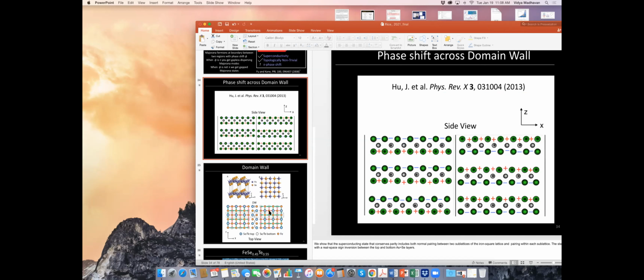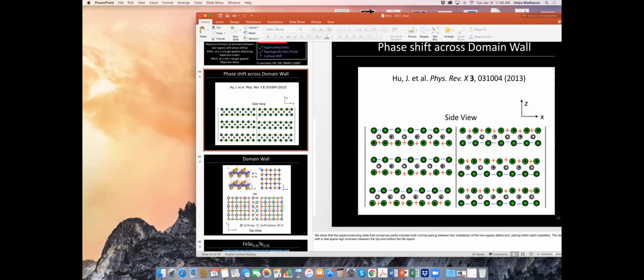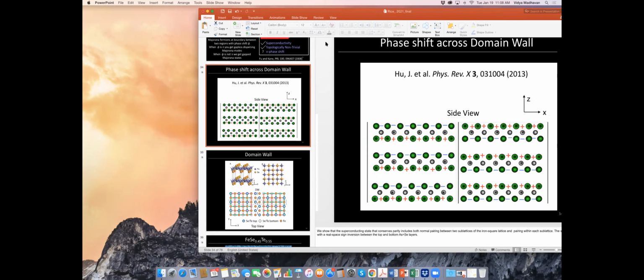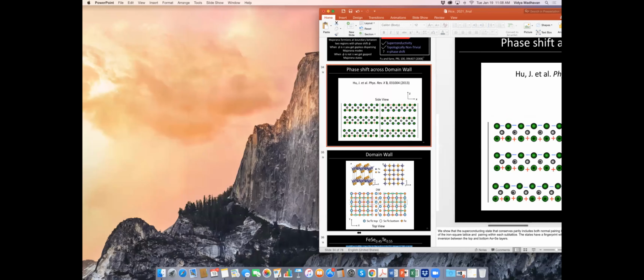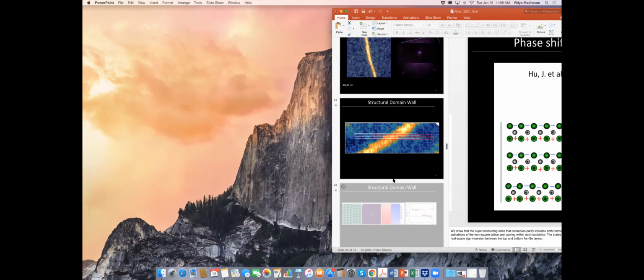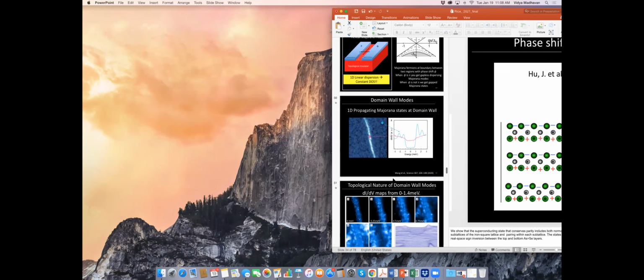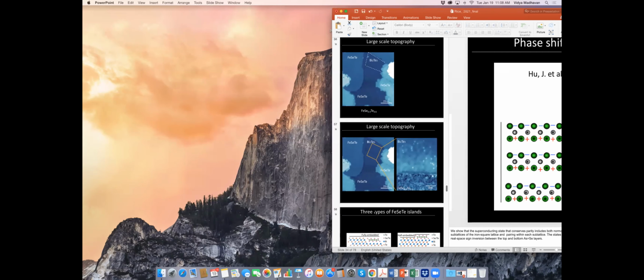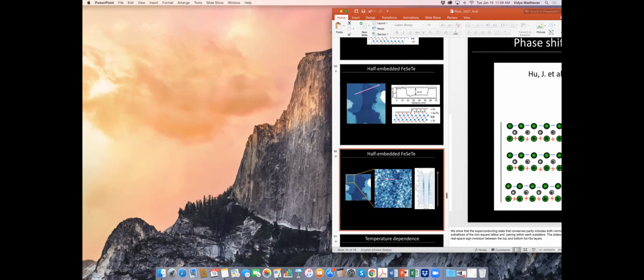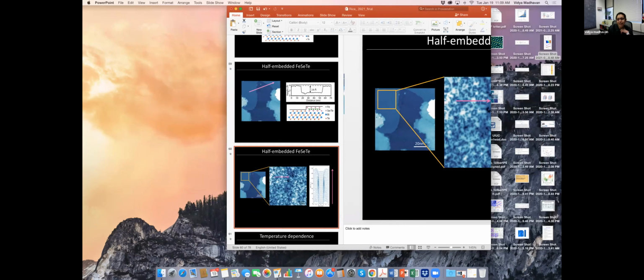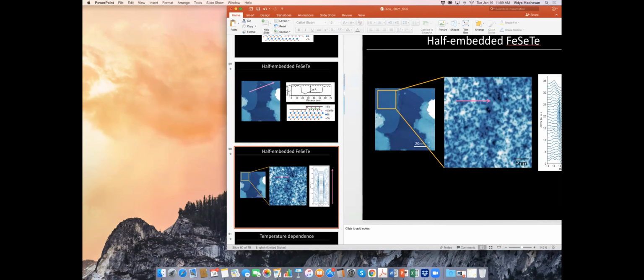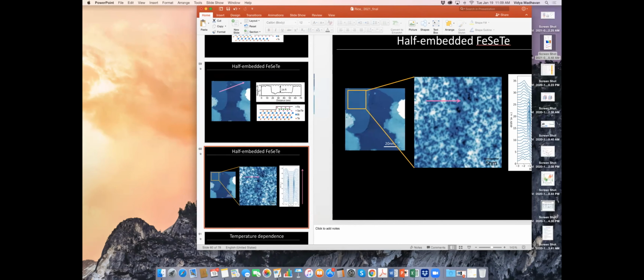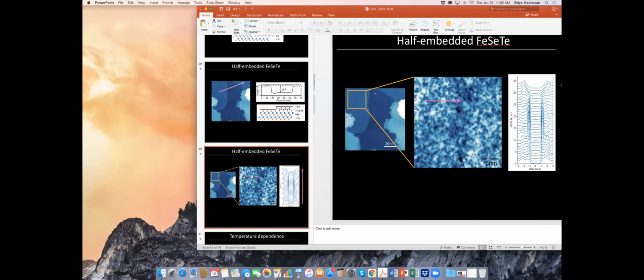Yeah, thank you very much for your very nice talk. I have a question regarding the growth of this iron selenium tellurium 50-50. You said that you can grow these materials without interstitials or iron excess. I find it a bit strange because that material actually allows iron excess in the lattice, and normally people anneal the samples, and still if you anneal it, it's not guaranteed that you get rid of the excess of iron. So I'm puzzled, also from the phase diagram point of view, it's surprising to me that one can access it.